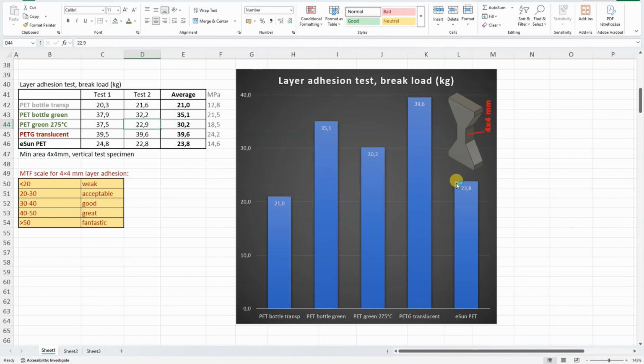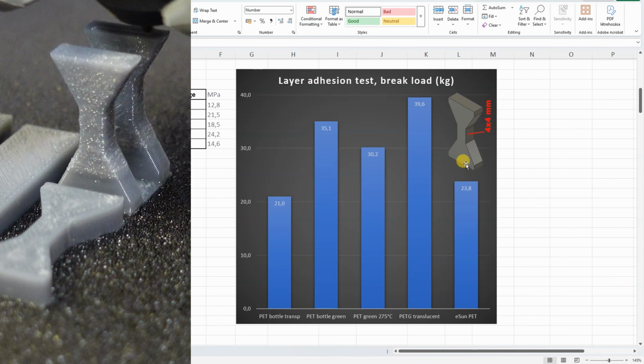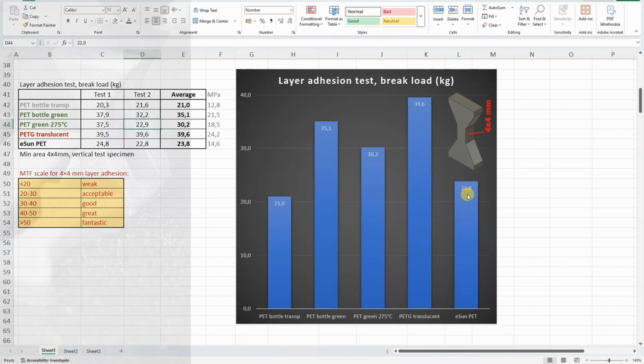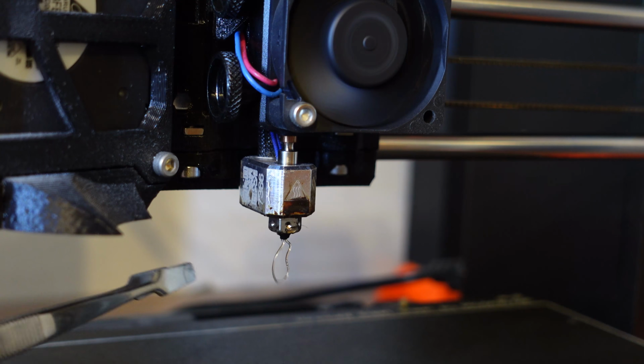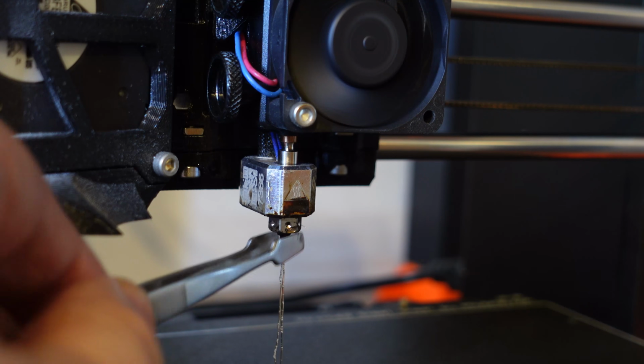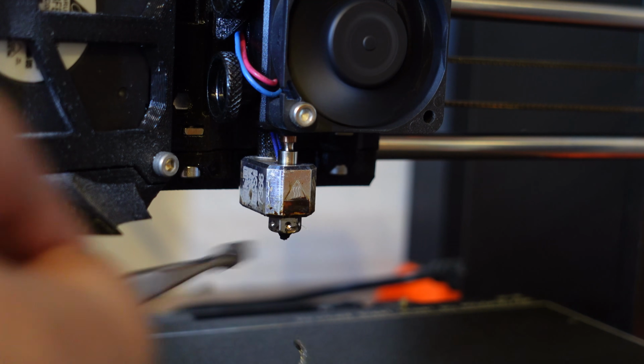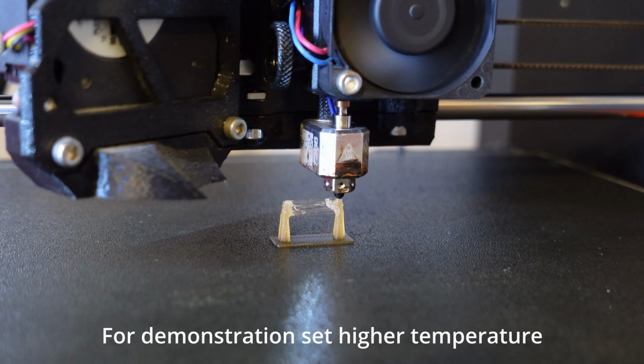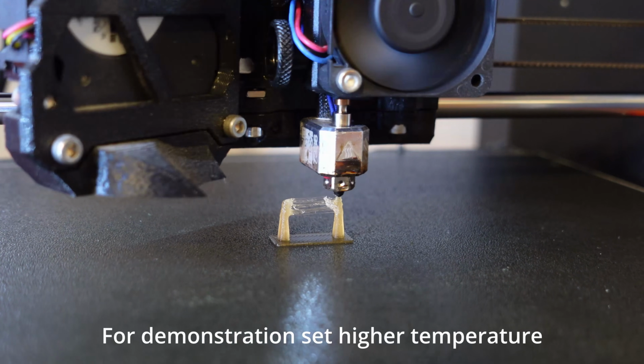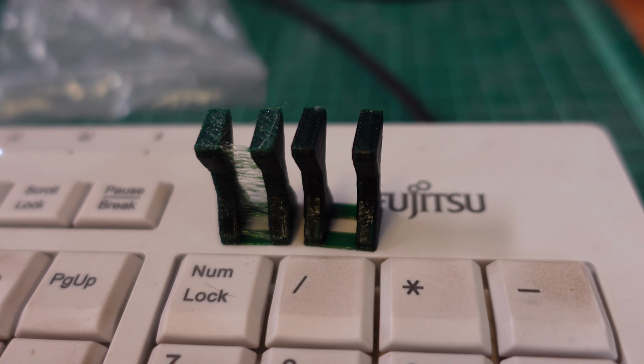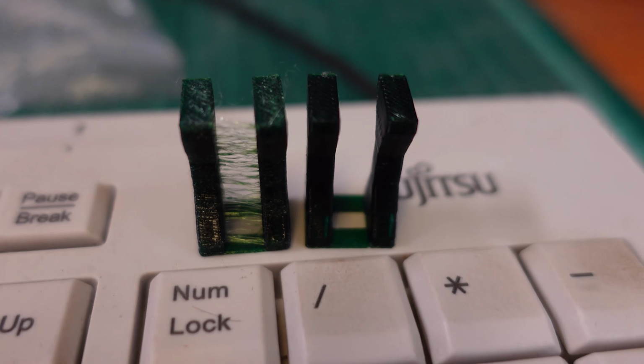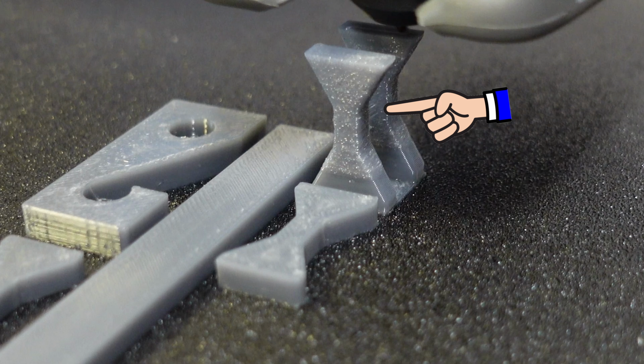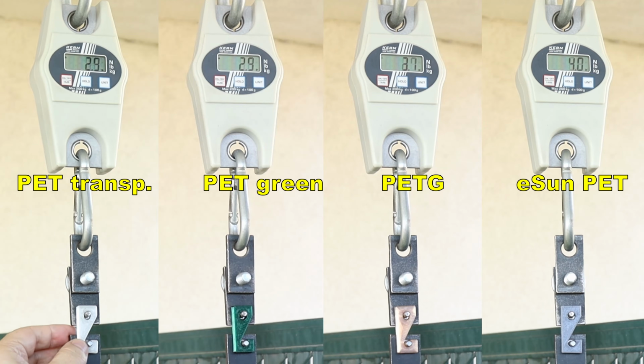And then eSun PET. This is a little bit weaker compared to that review video, but in the review video I didn't have the stringing, and I have it now. And let me explain you why this is important for the layer adhesion. The stringing is oozing from the nozzle, but the head is moving from one location to other. The oozing is lost material, but it will not be compensated with the extrusion. So that material you see in the stringing should be part of the printed object. That's why stringing, because of the wet filament or too high temperature, may result in weaker layer adhesion. Hooks side by side all four.